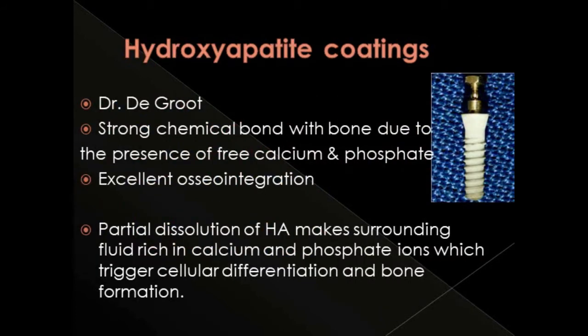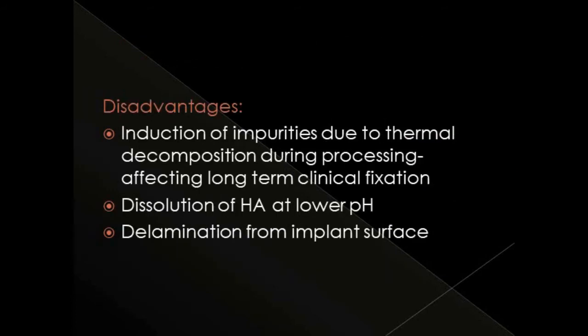The first additive surface characterization is hydroxyapatite coating, introduced by Dr. De Groot. The main advantage is that it forms a very strong chemical bond with the bone due to free calcium and phosphate, resulting in excellent osseointegration. There is also partial dissolution of hydroxyapatite which makes surrounding fluid rich in calcium and phosphate ions, triggering cellular differentiation and bone formation. Disadvantages include impurities from thermal decomposition, dissolution at lower pH, and delamination of the coating from the implant surface.